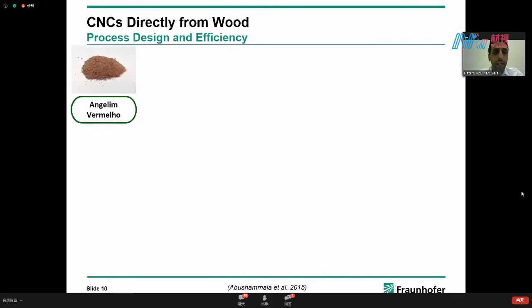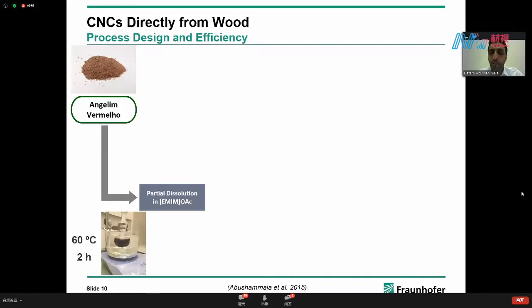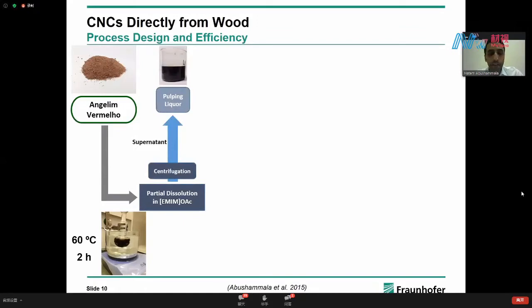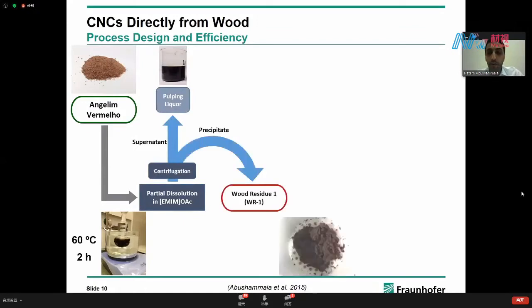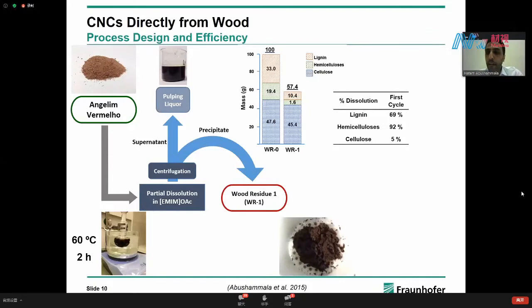And in this work, I used an Amazonian wood from the Amazonian region, since this project was a German-Brazilian project. The wood is called Angelim Vermelho, and we treat it with the ionic liquid at pretty much mild temperature and time. And then the pulping liquor was separated simply by centrifugation, and then we got this wood residue. And we noticed that we were able to actually pulp the wood pretty efficiently. So around 90% of the hemicellulose was removed, and around 70% of the lignin was removed.